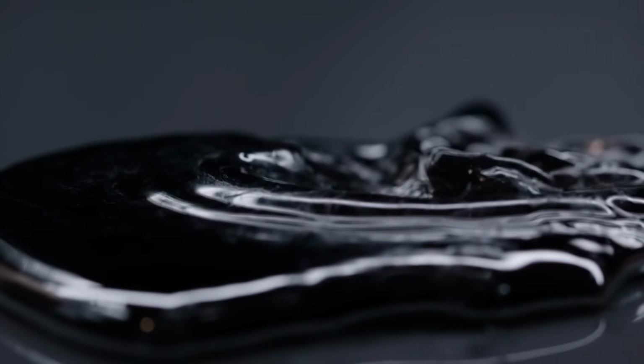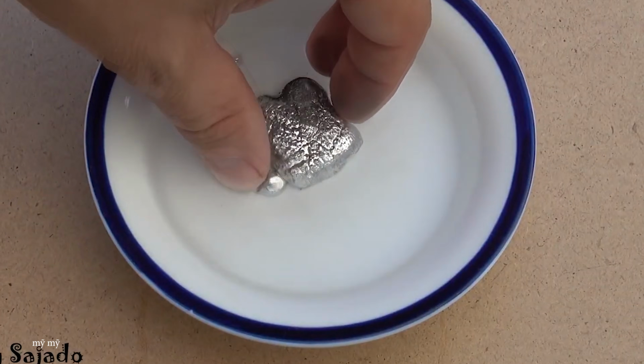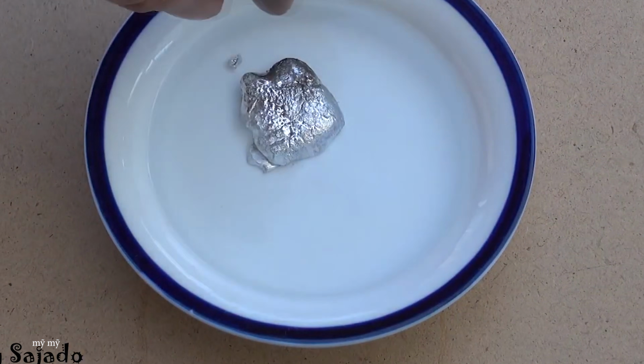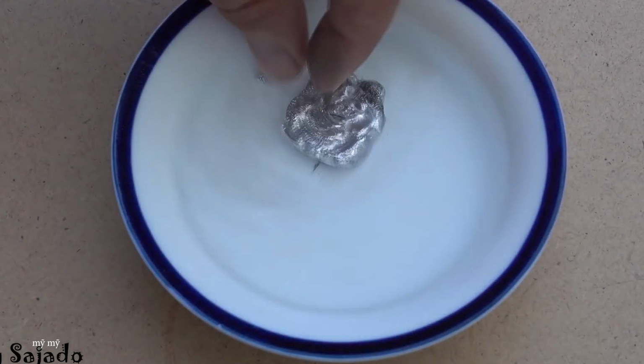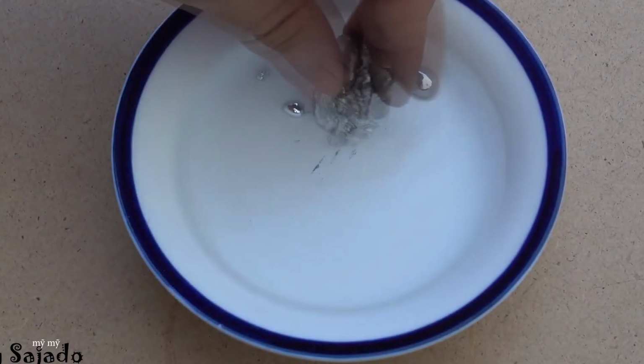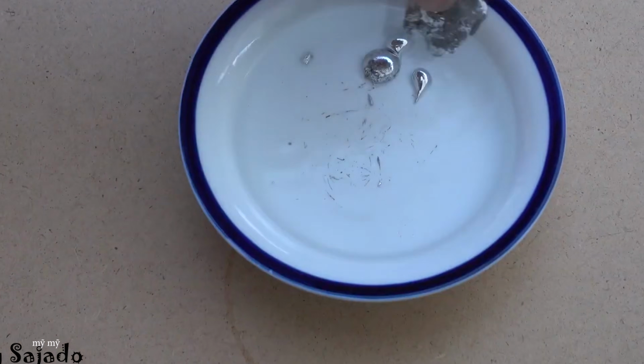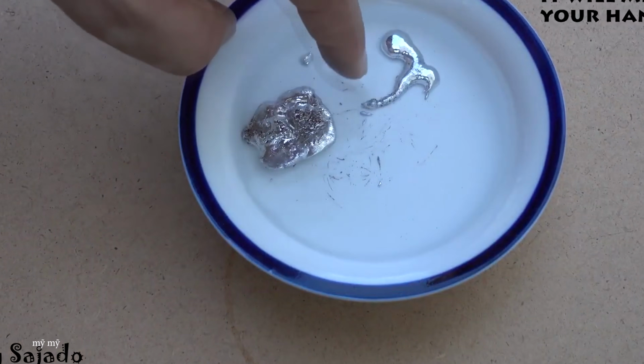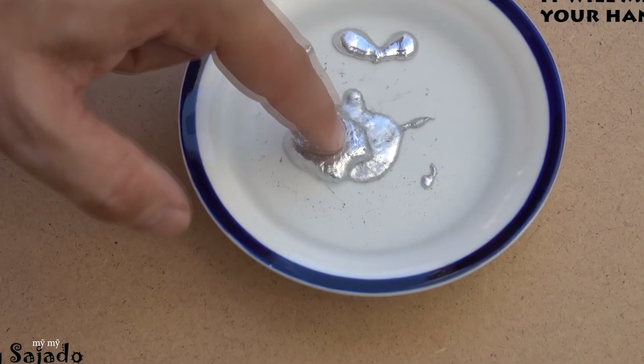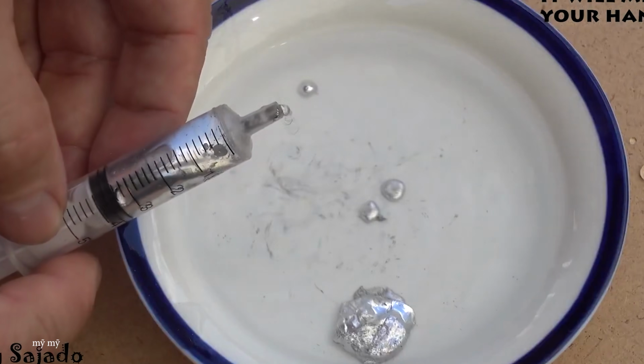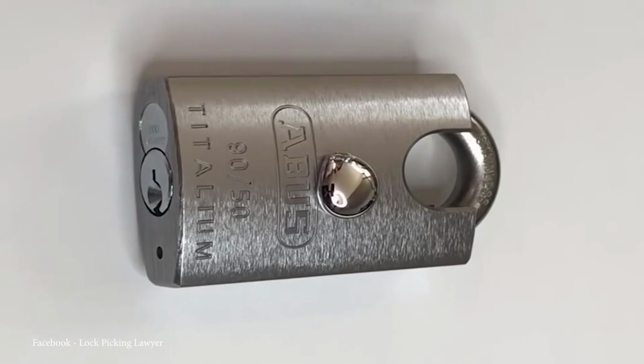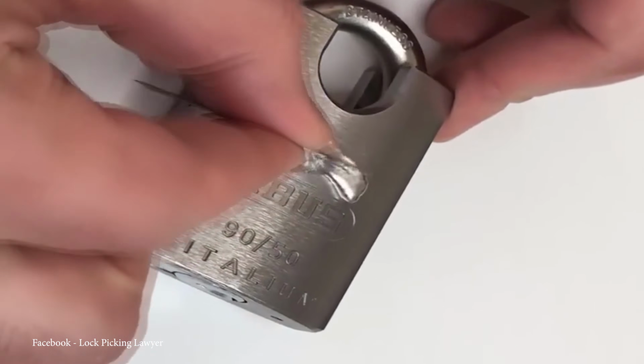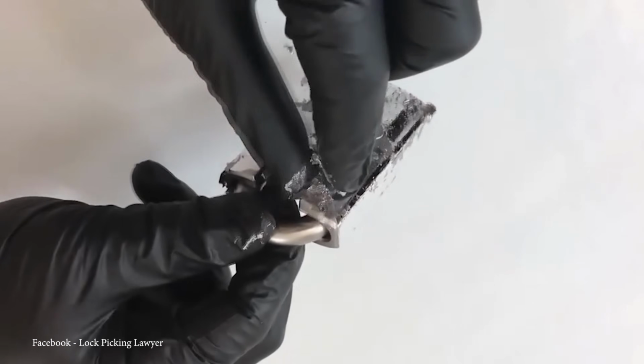Unlike mercury, which remains metallic and shiny across many temperatures, gallium doesn't form a persistent surface oxide layer, so its surface appearance can vary depending on the exposure to the air. It can wet many materials, including glass, much more readily than mercury does. This kind of wetting behavior is one reason gallium can corrode aluminum so quickly. When gallium does come into contact with aluminum, it disrupts the protective oxide layer, allowing the liquid metal to penetrate grain boundaries and break down the metal.